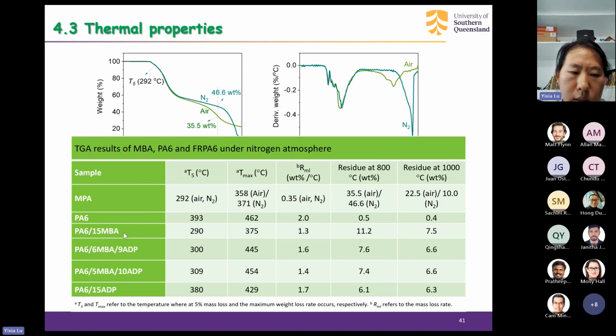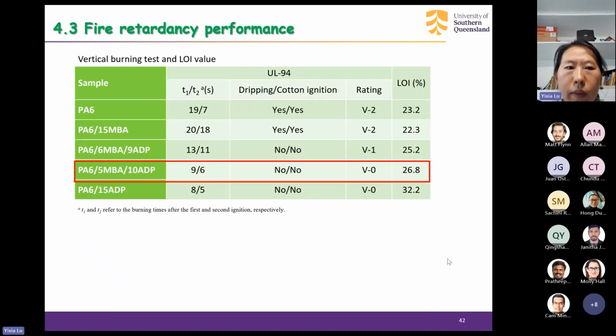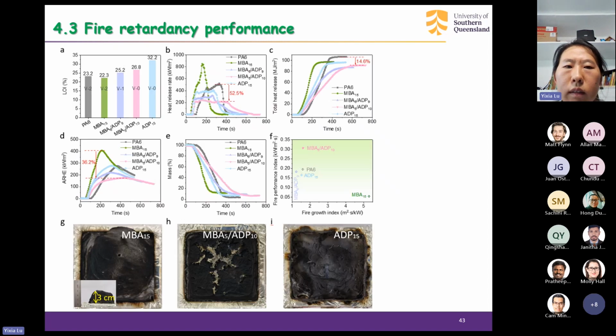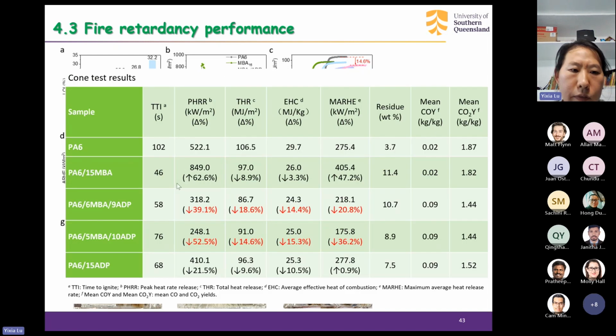The sole use of 15% of MBA, and the other two components are 6% of MBA and 9% of ADP, and 5% of MBA and 10% of ADP. The amounts are close, but we find some difference between them. For the vertical burning test and the LOI value, this table says the composite containing 5% of MBA and 10% of ADP performs better than the other components, but 15% of ADP performs best, as the LOI value says. But the cone results are a little bit different.